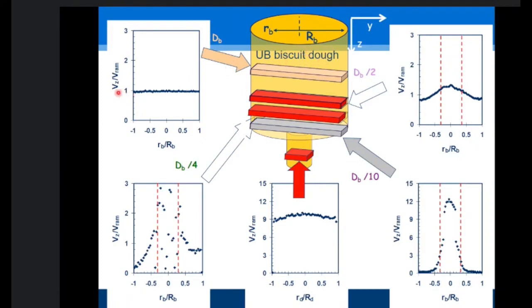What we can see here is the velocity in the downward direction, z, divided by the RAM velocity. Up here, you can see that it's this value of 1. That means that everything is moving at the RAM velocity, which means it's moving in plug flow. The scale here is the radius divided by the radius of the barrel. So as you can see, apart from right up against the wall, everything is moving at the same speed, which means we've got almost total slip at the wall.